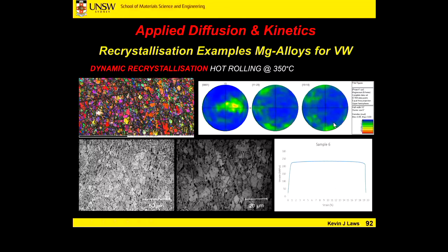We can see from our pole figures here that we don't really have those localized spots in these two planes anymore. It's actually very random where these spots are occurring. They're at different places compared to the other one, if they are localized. On our basal plane we are getting a slight concentration. So we've changed the texture of our material through recrystallization.